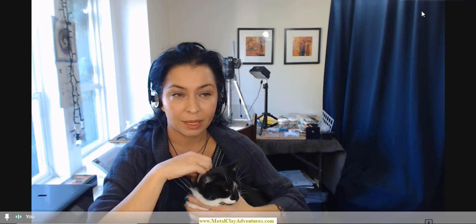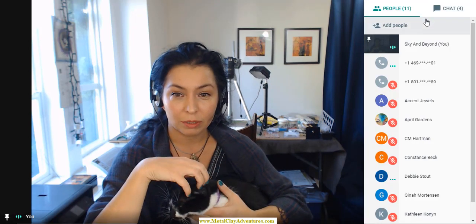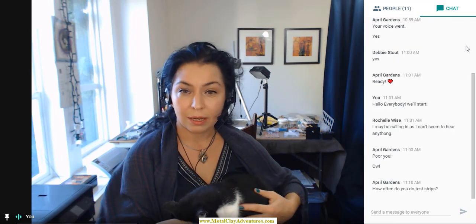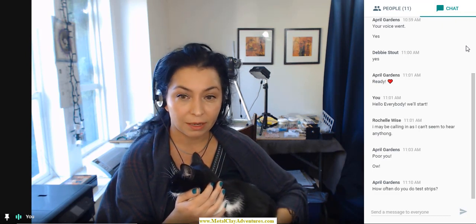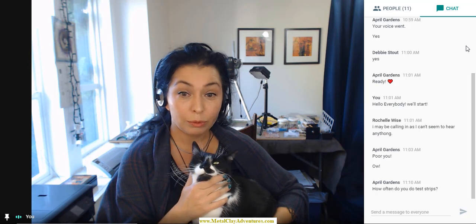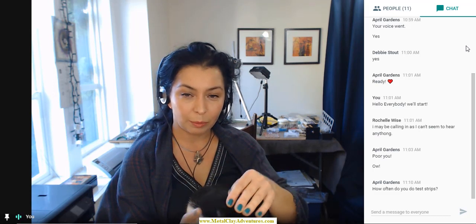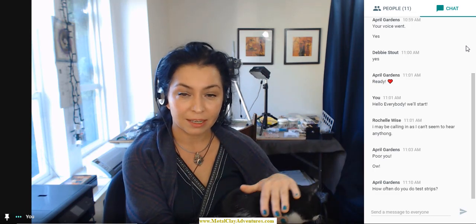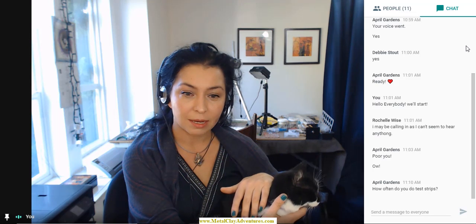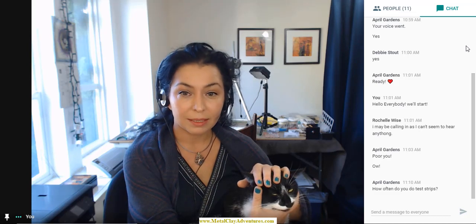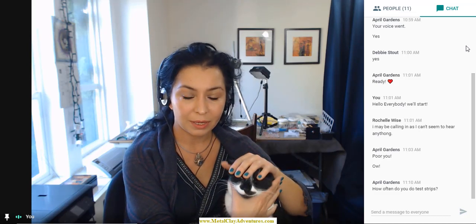are very predictable. If I'm sintering alloys, and I am talking about alloys which contain more than 5% copper, about sterling silver 925, I will be test firing every time I am putting a masterpiece in the kiln. This means that I will be placing in the kiln the masterpiece and the test strip, so I can check the test strip before taking out the masterpiece. If I am firing base metals, the same. I am test firing every time I am sintering base metals, masterpieces.